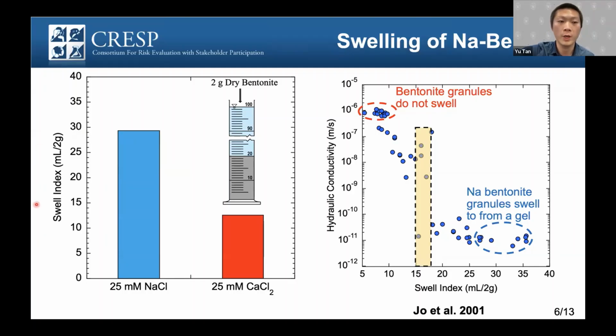We usually use swell index tests to evaluate the swelling of bentonite, and also as an indicator for the hydraulic conductivity of GCL. For the swell index test, we have a graduated cylinder, and we pre-fill the solution we would like to evaluate into the cylinder. We have 2 grams of dry bentonite. We add the bentonite into the cylinder and let the bentonite swell. Finally, when it reaches equilibrium, we record the volume of the bentonite at the bottom. This is the maximum volume that the bentonite can reach in the specific solution. We report that volume of bentonite as the swell index. It indicates the swelling capability of the bentonite.